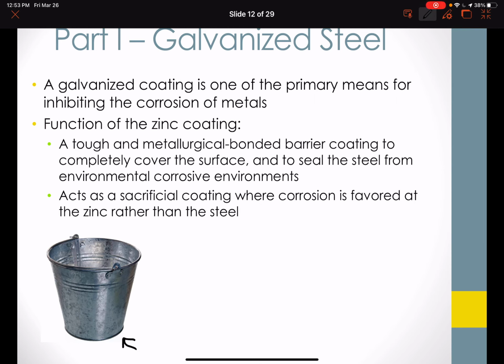So the function of this zinc coating is ultimately to act as a tough bonded barrier, one that covers the complete surface and will seal the steel or the metal structure away from the environment, kind of environments that are often very corrosive. Okay, so this sort of acts like a barrier or a skin around the structure at the very least. The bonding is at the metallurgical level, or that is to say it's often alloyed, so the bonding is very good if the zinc has been applied correctly.